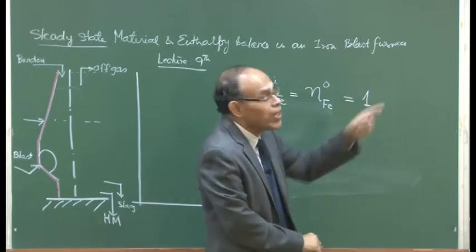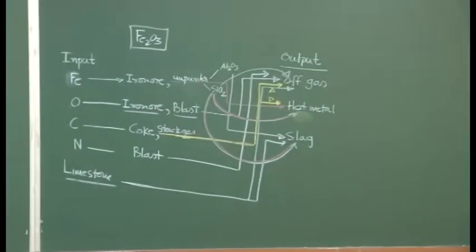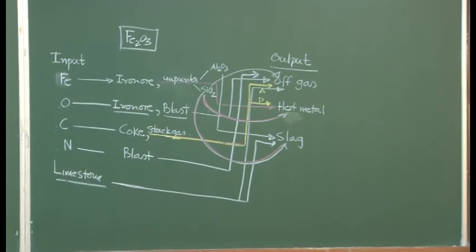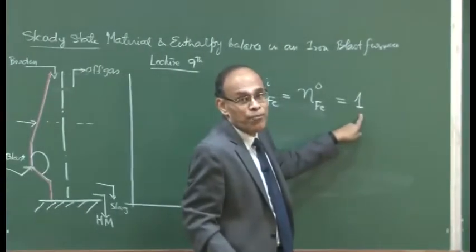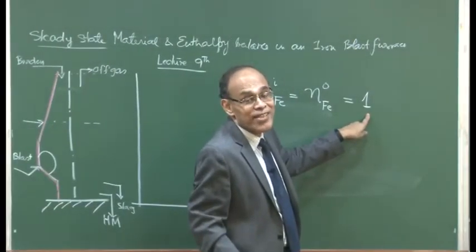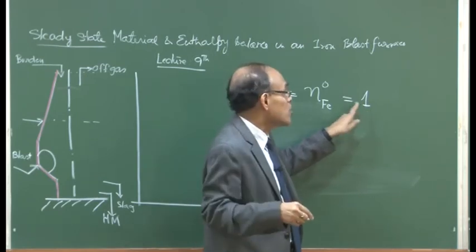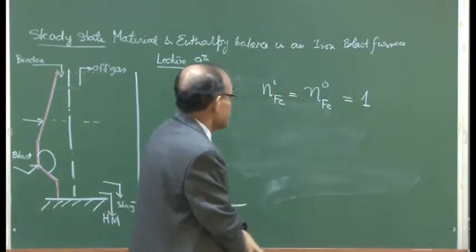It is evident looking at the formula of the compound that it is only half mole of Fe2O3. If I charge that into the furnace, then that half mole of Fe2O3 will give me the 1 mole of Fe, okay? Because there is no Fe present in the slag, and we have ignored any material loss, therefore the total iron conservation is there.